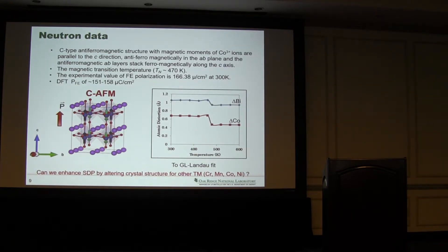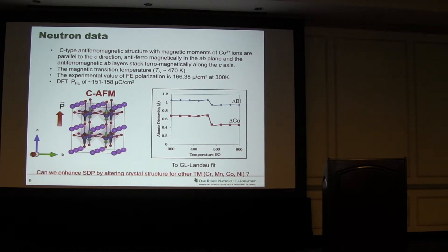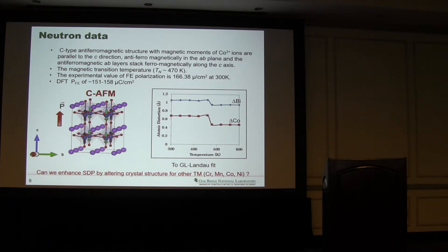We have methods that we can extract the spin-driven polarization by comparing the anti-ferromagnetic ordering and ferromagnetic ordering, and it turns out that it has 2.59 µC per centimeter squared — comparable to bismuth ferrite. Bismuth ferrite has octahedral rotation, but bismuth cobalt oxide doesn't have any rotation here. So without rotation, bismuth cobalt oxide in ground state already has large spin-driven polarization. We have neutron data, which also shows C-type anti-ferromagnetic ordering and a Néel temperature. Using those data, we can estimate the polarization — around 166 µC per centimeter squared at 300K. DFT is also giving a similar result, though it may vary depending on the U value and the functional used. We have the distortion as a function of temperature from neutron data, and from here we can confirm that there is large spin-driven polarization, though we haven't obtained refined data to get the quantitative accurate spin-driven polarization number.